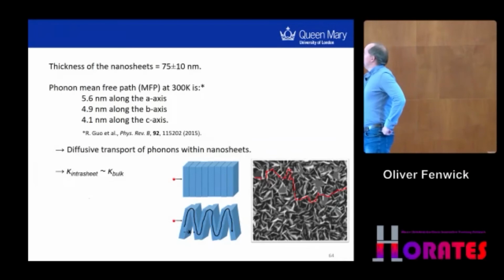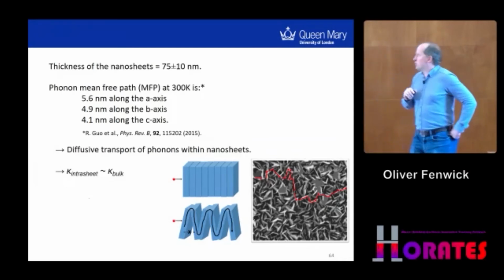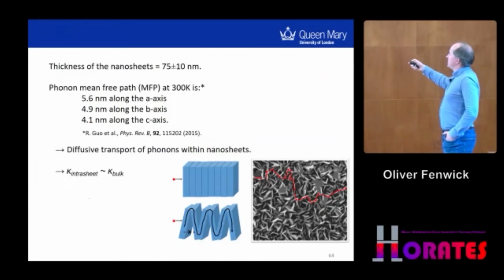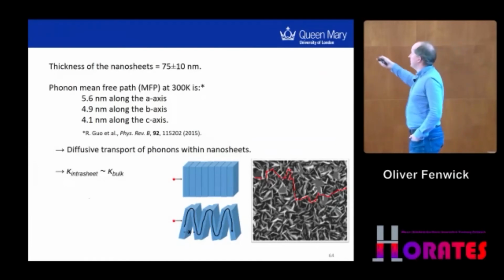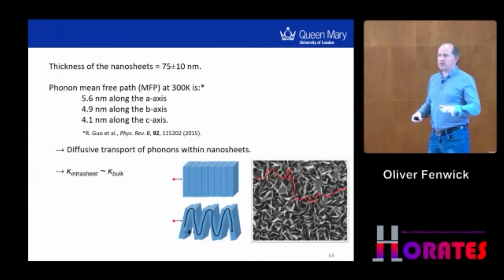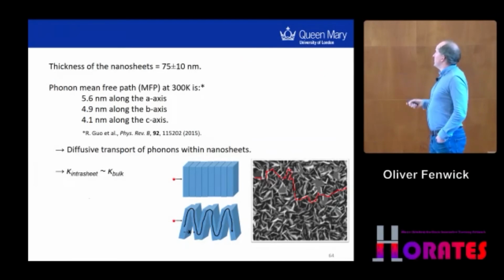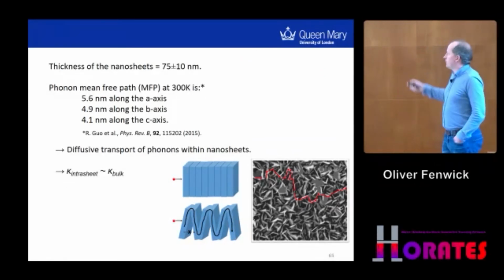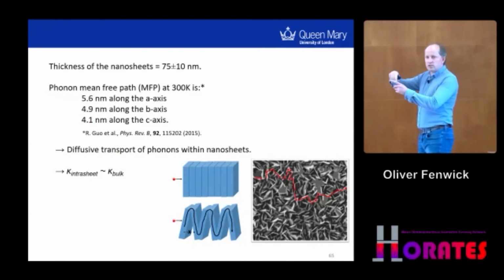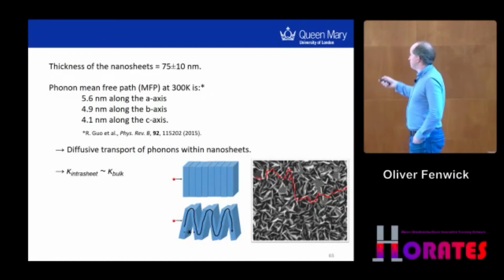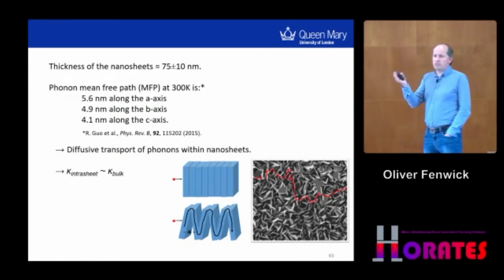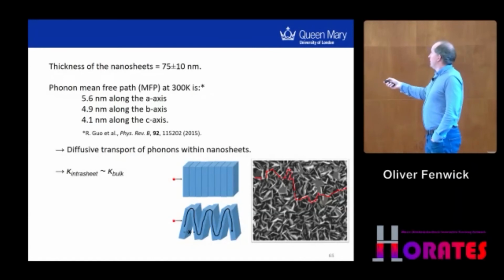So what's happening to phonons inside these sheets? If you look in the literature, we found that the reported phonon mean free path in tin selenide is around 5 nanometers. The thickness of the sheets is around 75 or so nanometers. So within a sheet, the heat's still moving in a diffusive way, so boundary scattering on the sheets shouldn't be a big issue. Or put another way, the thermal conductivity within the sheet should be roughly the same as the intrinsic bulk material.